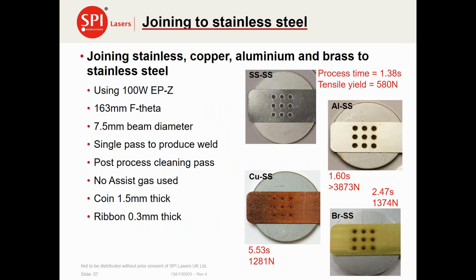Here are some particular examples, again using the spiral method of spot welding. In this case, we're joining stainless steel, copper, aluminium, and brass to stainless steel. In red, you can see the process time. This is the full process time for all 9 spot welds, not just per spot weld, and the tensile yield test for each of these welds. Again, down the left-hand side here, you can see the common parameters which were used during the process, just for reference.